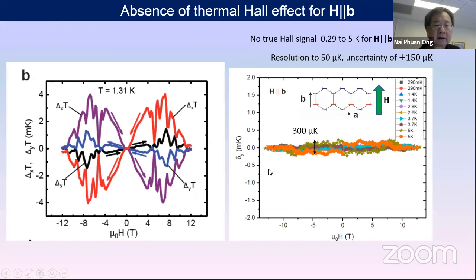All right, now coming to ruthenium chloride, at low temperatures with the magnetic field parallel to the zigzag direction, we find that even though the fictitious thermal Hall signal is very large, after using the technique that I mentioned, you see that the intrinsic thermal Hall signal is 0. And this illustrates the resolution of our experiment as well as the uncertainty.